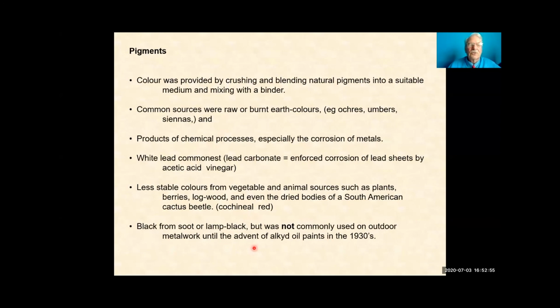Black from soot or lamp black was not commonly used on outdoor metalwork until the alkyd oil paints arrived in the 1930s. If you mix soot with one of these binders, it comes out gray, not real black.